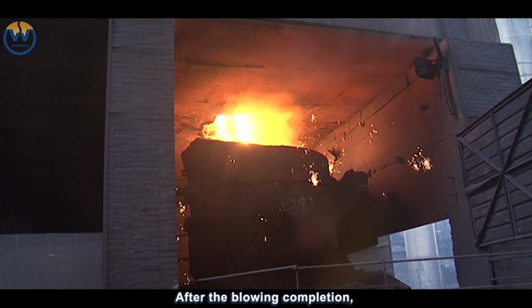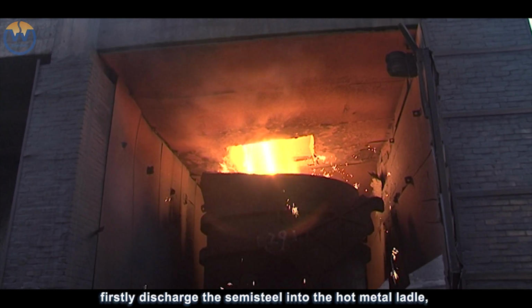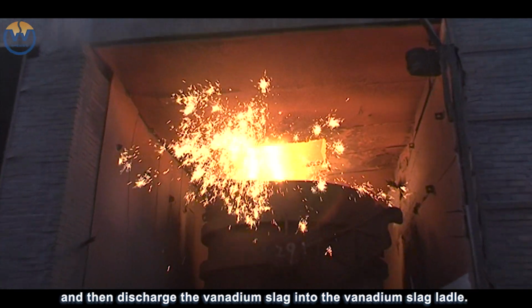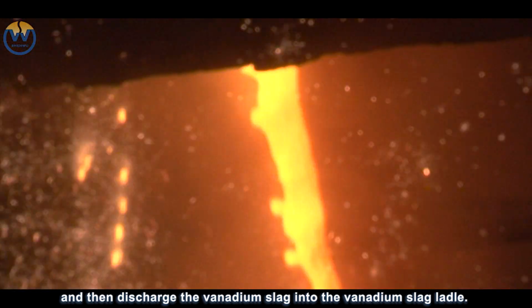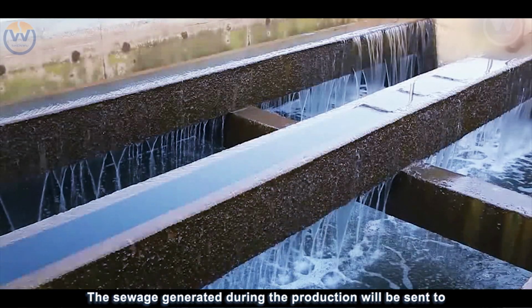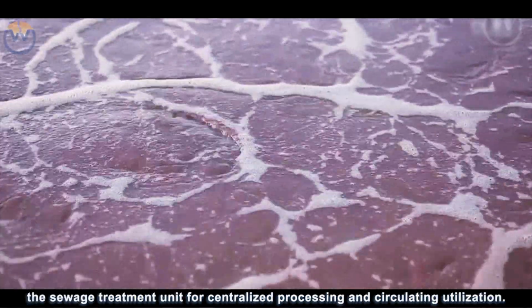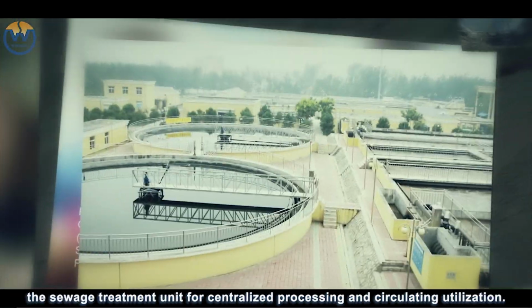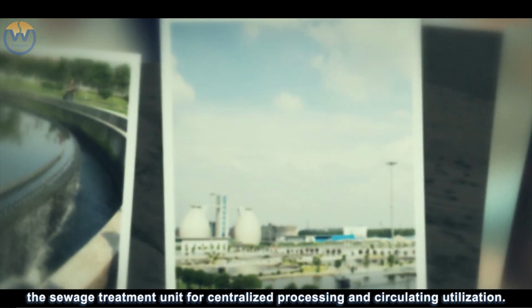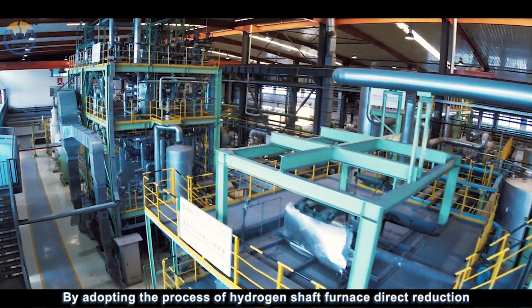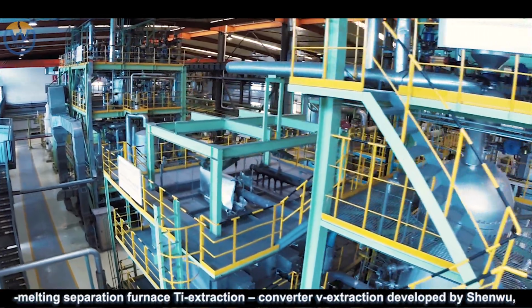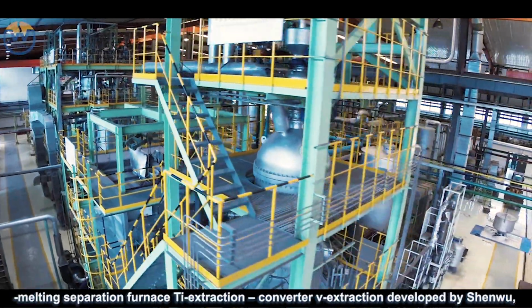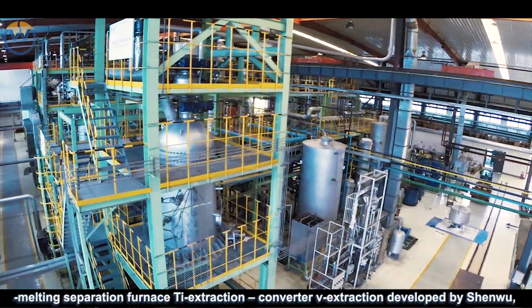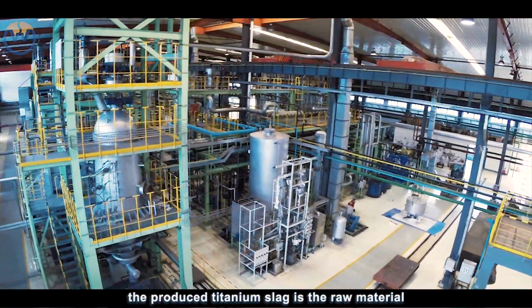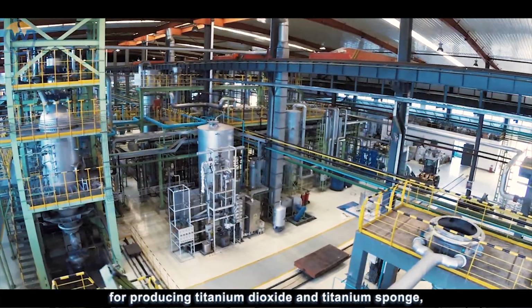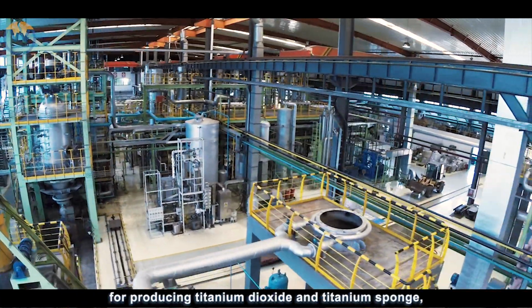After the blowing completion, firstly discharge the semi-steel into the hot metal ladle, and then discharge the vanadium slag into the vanadium slag ladle. The sewage generated during the production will be sent to the sewage treatment unit for centralized processing and circulating utilization. This is achieved by adopting the process of hydrogen shaft furnace direct reduction, melting separation furnace Ti extraction, converter V extraction developed by Shenwu. The produced titanium slag is the raw material for producing titanium dioxide and titanium sponge.